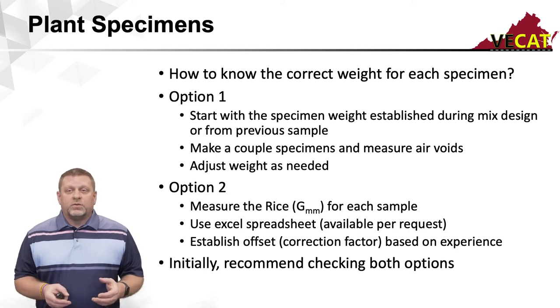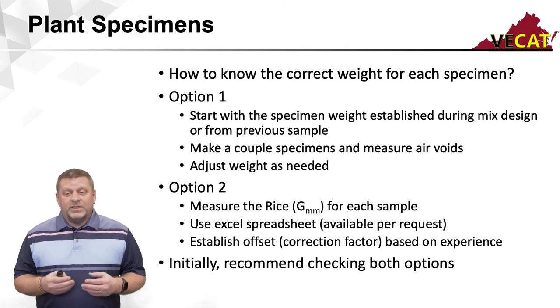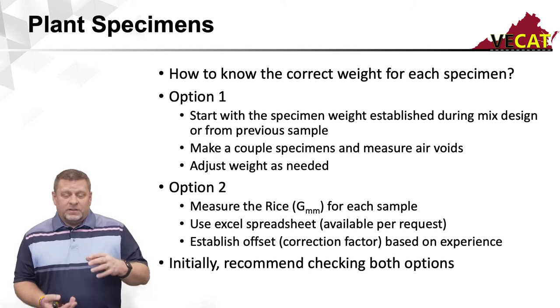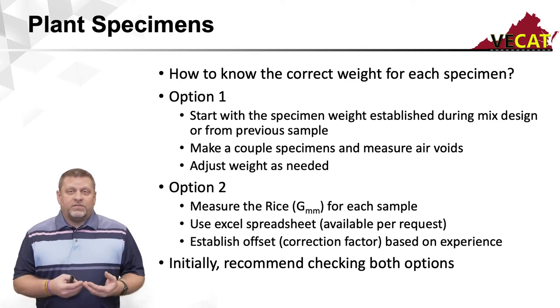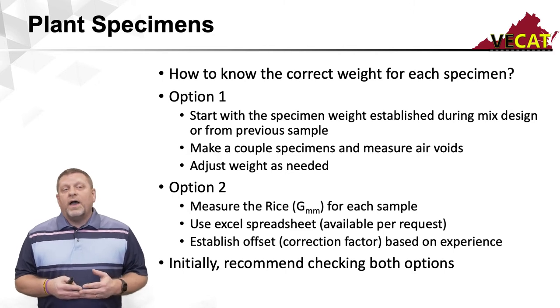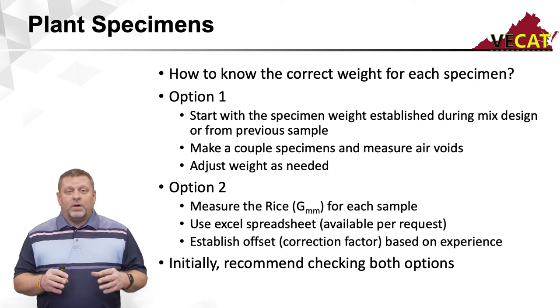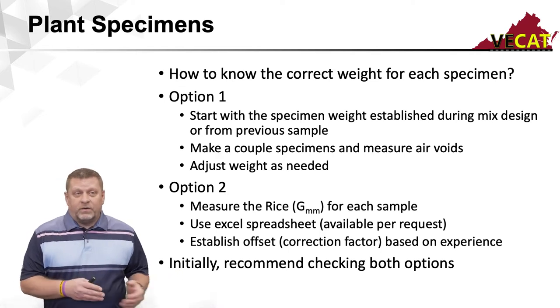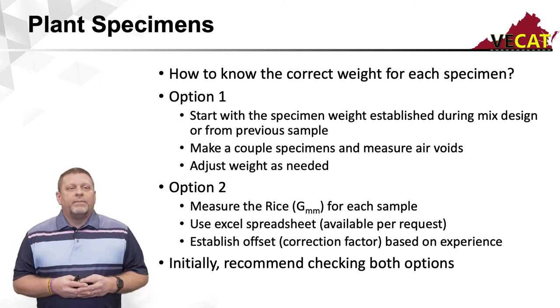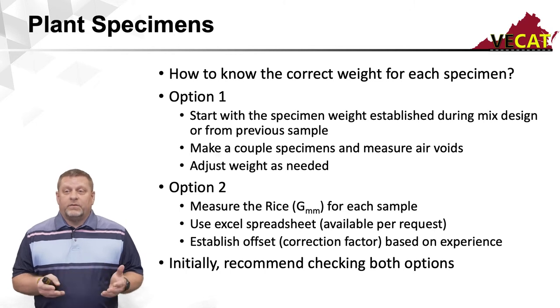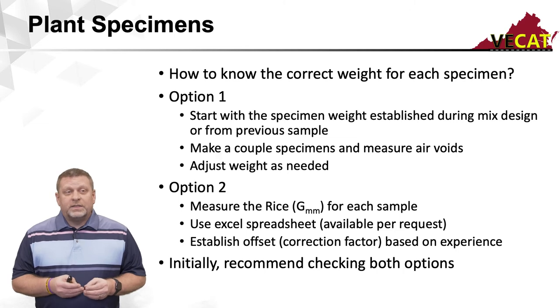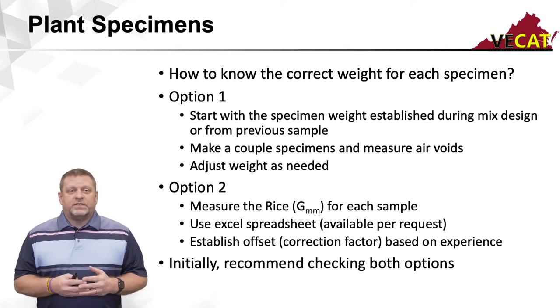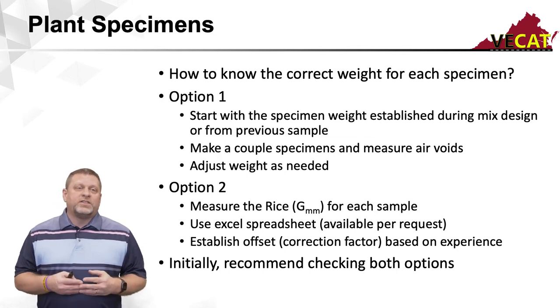What you want to do is make about two pills quickly, cool them down as fast as you can. For quick cooling, I've seen people use fans with the sample suspended above the tabletop so air flows all the way around, or portable air conditioners blowing conditioned air across the sample. You want to measure air voids as quickly as possible so you can split out the remainder of your testing specimens. This allows you to adjust the weight as needed depending on the void range you achieve. Another option is to measure the rice for each sample and calculate it using a standard Excel spreadsheet with formulas that calculate a target weight for the void range for each test procedure.